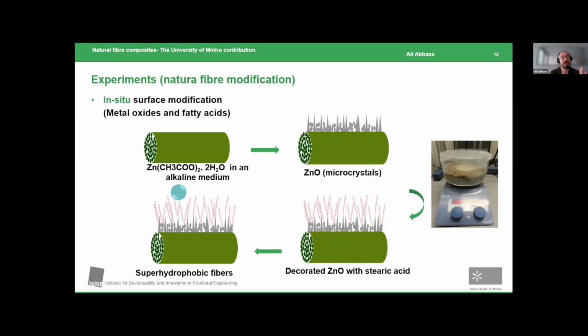So first, simply you would have a container with zinc acetate dihydrate, and you would have it in an alkaline medium in a buffer to control the alkalinity. Then you would put the lignocellulosic material at room temperature. You let it sit overnight, then you will have this beautiful microstructure. You have different phases. You have microrods, microlamellas, microspikes grown onto this lignocellulosic surface. So up to now, we didn't achieve any wettability advantage. We only achieved the morphological improvement.